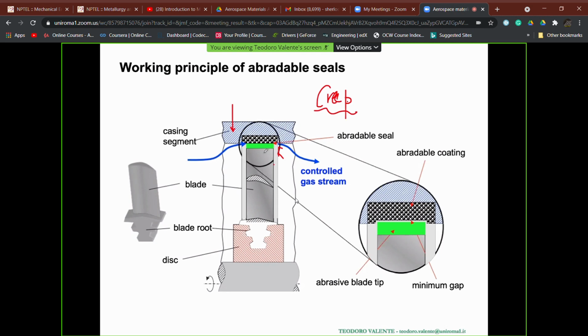Without having failure due to the impact of the blade on the fixed part, that is, on the casing. Since we know how to evaluate over time, at least for the stationary part of the creep, how high the plastic and recovered deformation due to creep will be, the width of the gap between the tip of the blade and the casing segment can be directly related to the expected lifetime in terms of maximum hours of operation.